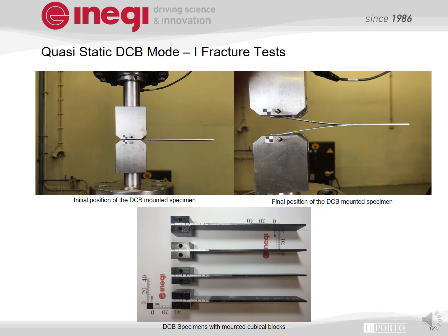The test stopped after reaching 50 mm of fracture length. In between, you can see the jaw profile when the fracture has propagated, and the top and bottom profiles are still attached to the loading blocks and made the shape of a jaw. You can see the fibers coming out of the surface area in between this profile.